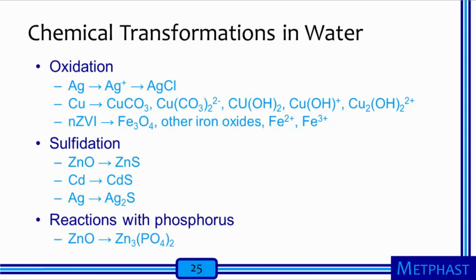In addition to these physical processes, engineered nanomaterials can also undergo chemical transformations when suspended in water. The most common transformations are oxidation reactions, sulfidation reactions, and reactions with phosphorus. Oxidation reactions include silver nanoparticles being oxidized to silver ions, which can then combine with free chlorine ions to form a salt. Copper nanoparticles can be transformed to a variety of carbonate or hydroxide complexes. Zero-valent iron nanoparticles can be oxidized to one of several iron oxides, which can release iron ions into the water. In examples of sulfidation reactions, zinc oxide, cadmium, and silver nanomaterials can be transformed to zinc sulfide, cadmium sulfide, and silver sulfide, respectively, in aquatic systems. An example of a reaction with phosphorus in water is transformation of zinc oxide nanoparticles to zinc phosphate.